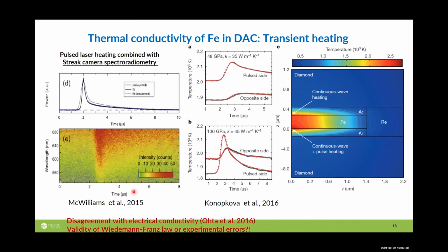So I would like to talk about the experimental techniques which we're using for measurements of alloys and minerals in the diamond anvil cell. What you can see here in the finite element calculation plot is that we essentially have a slab of material, maybe iron, maybe a mineral, and we laser heat it from both sides to get it to a certain temperature of interest. And you can see here the temperature, how it changes with time on a microsecond time scale.